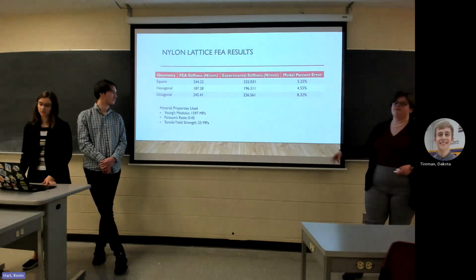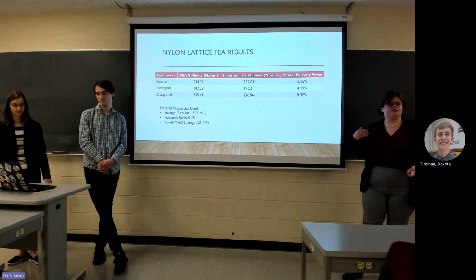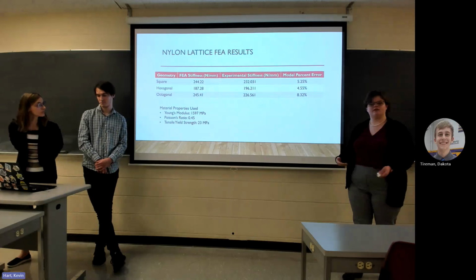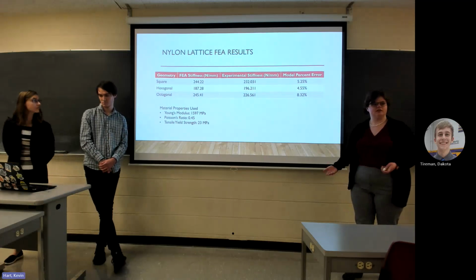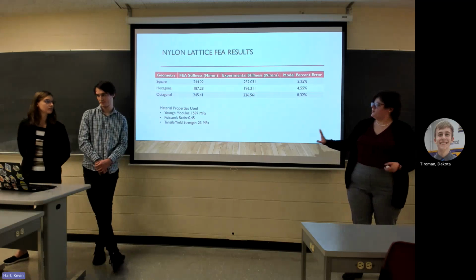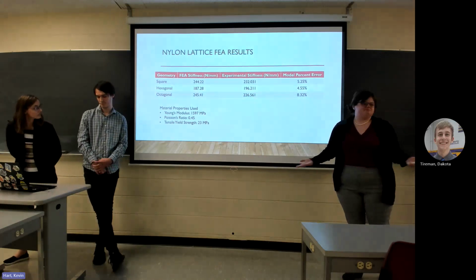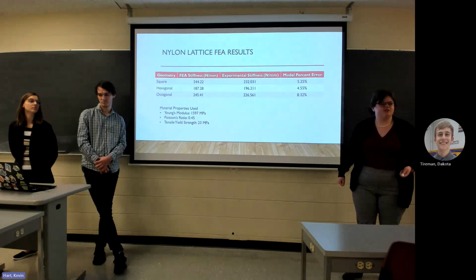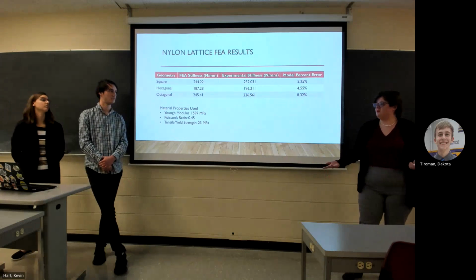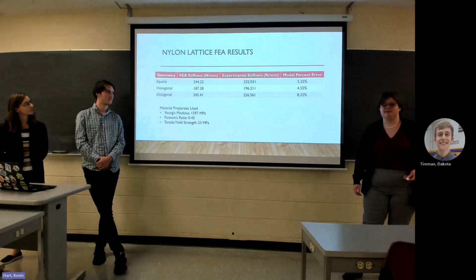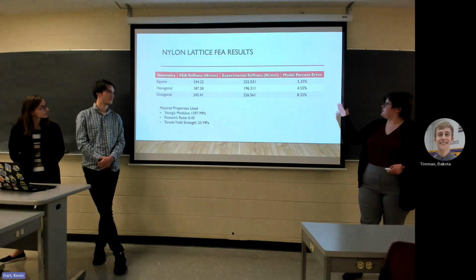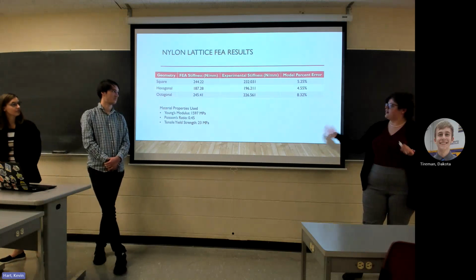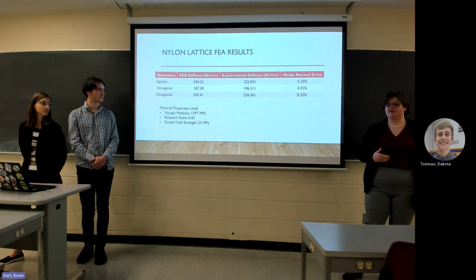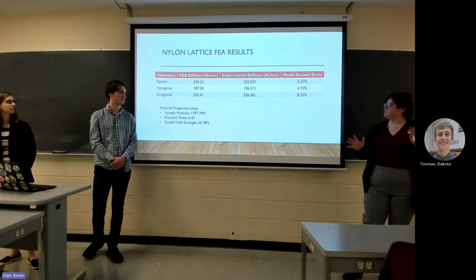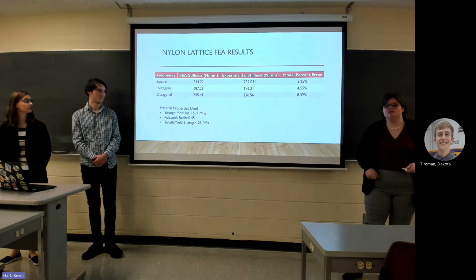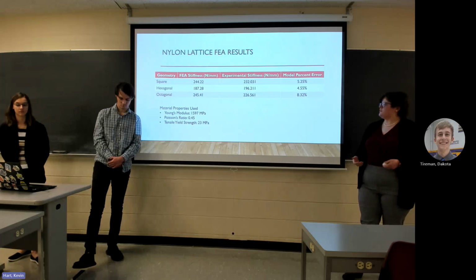Nylon 12 is a fairly linear material, so it was relatively easy to model. We put in the basic material properties for nylon 12 and it worked within a couple iterations. As you can see, we've got a percent error against the experimental data of all under 10% in terms of the stiffness.